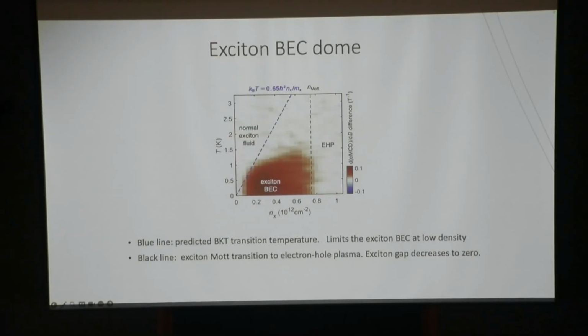We can also look at the overall phase diagram and see how it changes with densities. And we see the exciton BEC actually forms a dome-like structure. At small magnetic field and small density, it is constrained by this blue dashed line. It turns out this blue dashed line is a theoretical prediction for the BKT transition. But when you go to a higher density, of course, it deviates from the BKT behavior, up to a certain density, which is the critical density of the exciton Mott transition, where the total exciton gap goes to 0, and of course, the exciton condensate also disappears.